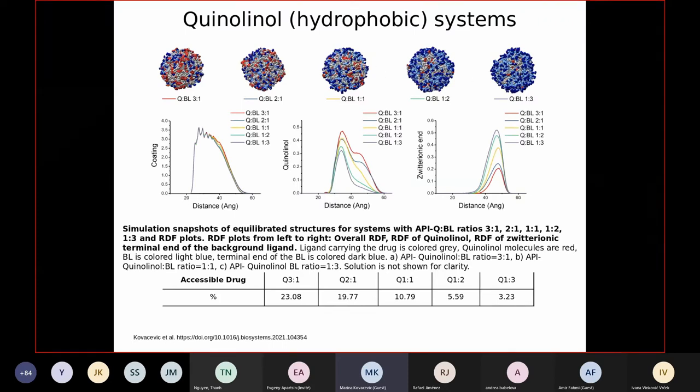So, even visually, when observing these snapshots, we can see a trend. As we increase the initial concentration of the ligand that carries the drug, we can see the higher amount of the drug accessible on the surface.